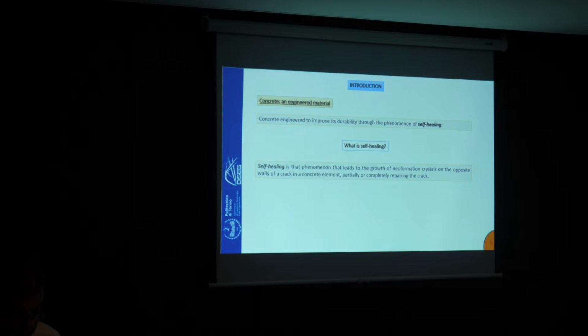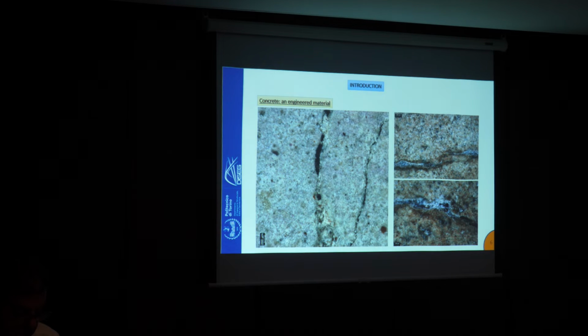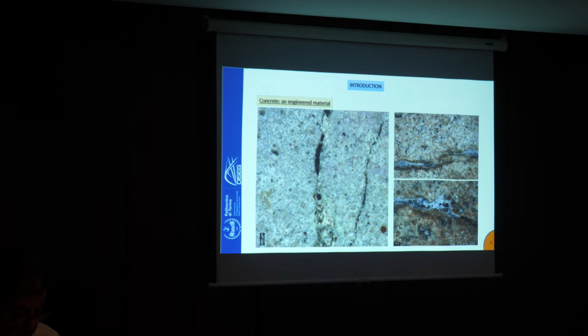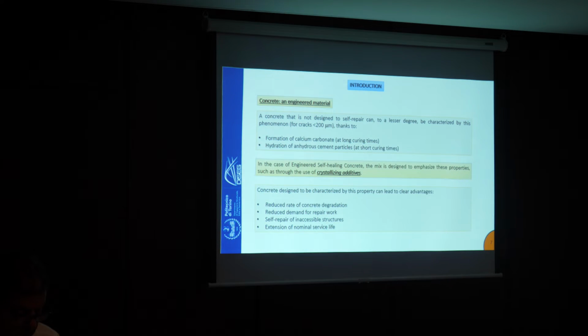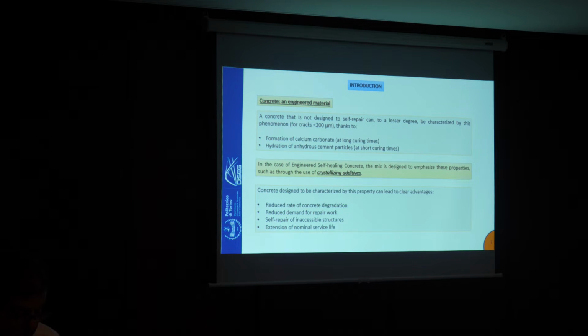We can improve durability of concrete through self-healing. What is self-healing? Self-healing is the phenomenon that leads to the growth of crystals on the opposite walls of cracks in order to partially or completely repair the crack. But we should emphasize that traditional concrete is also characterized by self-healing properties thanks to two phenomena: at short curing times, the hydration of anhydrous cement particles, and at long curing times, the formation of calcium carbonate.